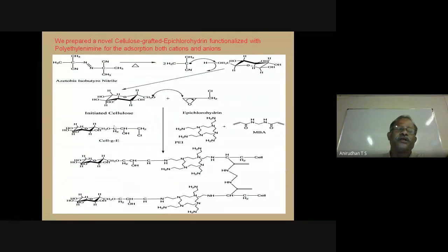This is a very important reagent which we utilize for manufacturing hundreds and hundreds of materials. The structure of azobisisobutyronitrile is this one, very simple. After breaking this bond, we have a radical, CH3 and CN C dot. This radical is highly reactive. As earlier, it abstracts one hydrogen atom from glucose, and we have a macromolecule like this. It will react with other reagents like epichlorohydrin. We have an epoxide ring, and this epoxide ring breaks, and an alcoholic OH group is formed, and we have cellulose grafted epichlorohydrin formed.